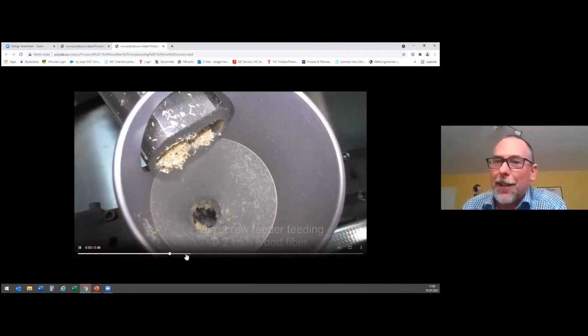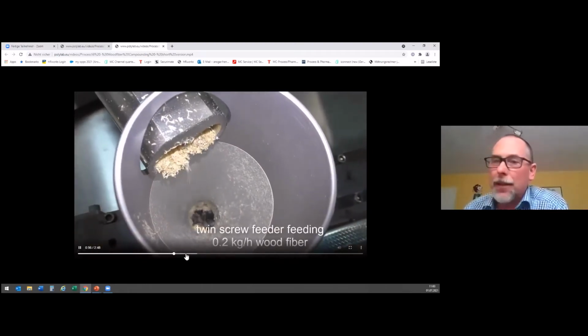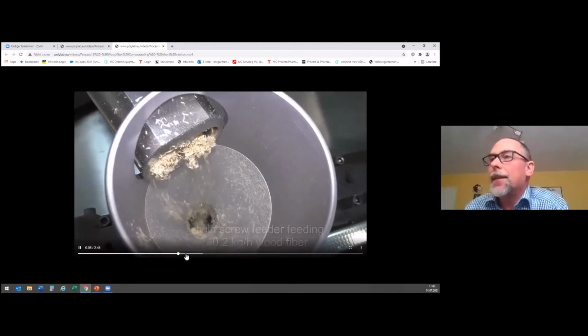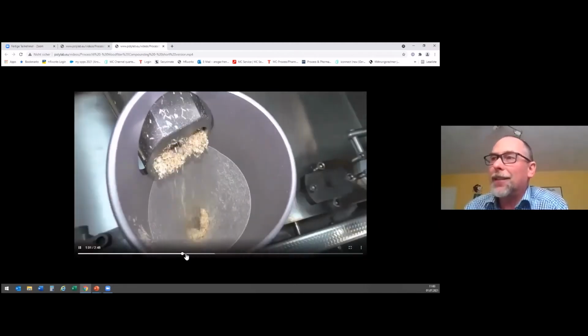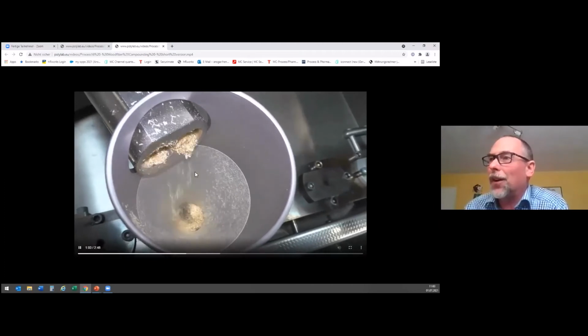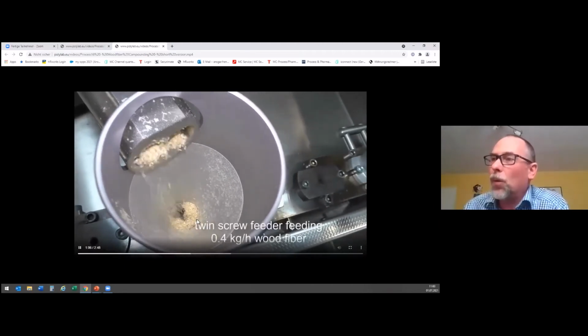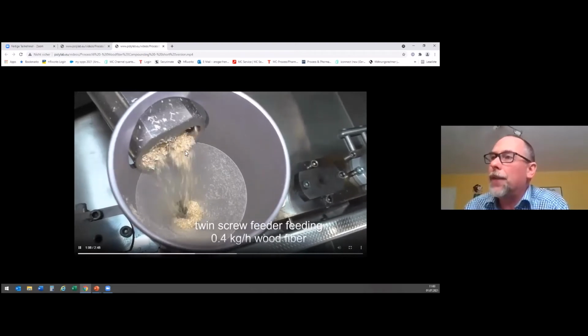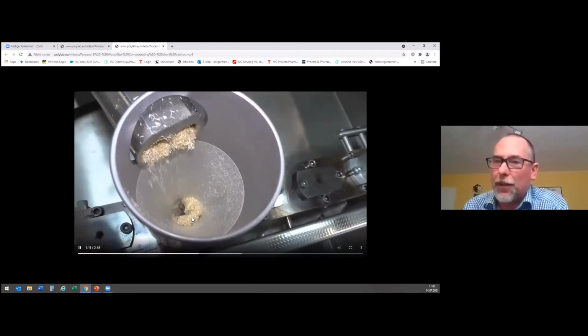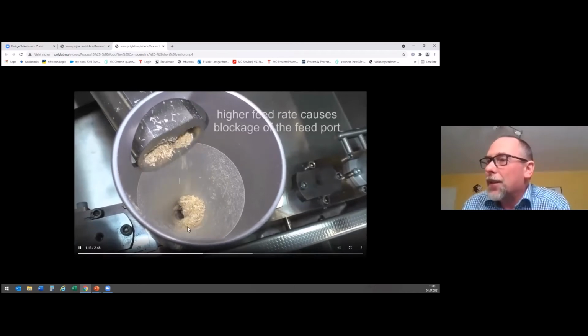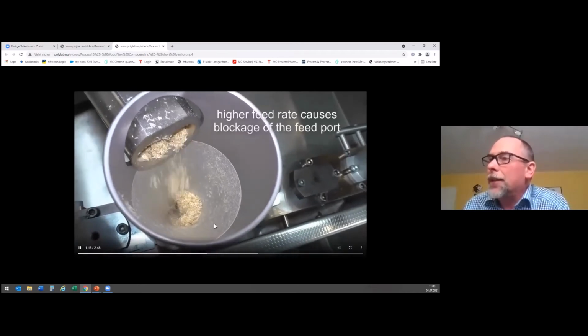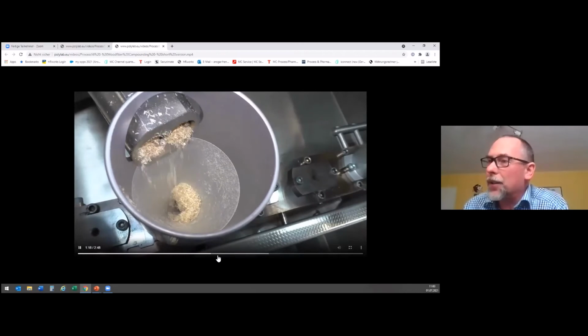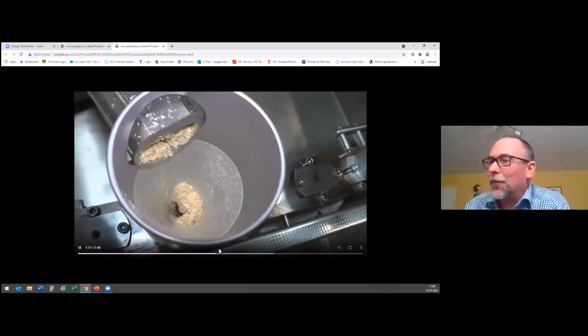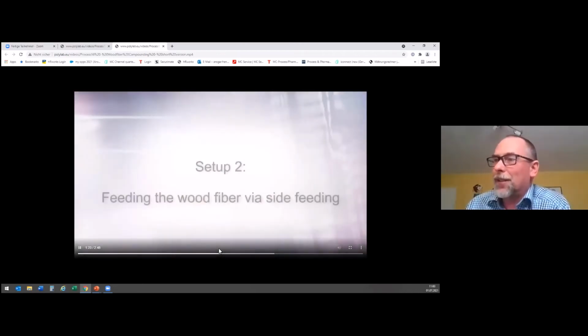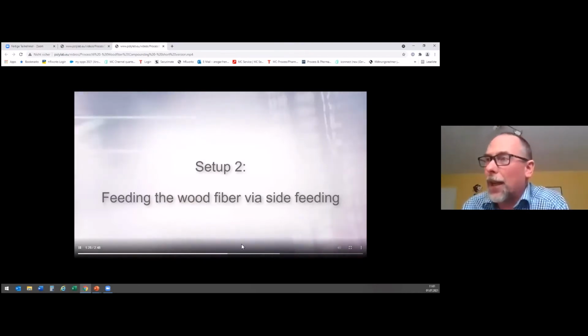Wood fibers are especially difficult because you can see they're very lightweight and they have a very bulky, sticky kind of feeding behavior. And what we will see, if we go too high in the feed rate, it will block the feeding zone. So here we get a little bit of unstable feeding behavior at higher throughputs. So that is made in this new system as an example of how important a side feeding could be.